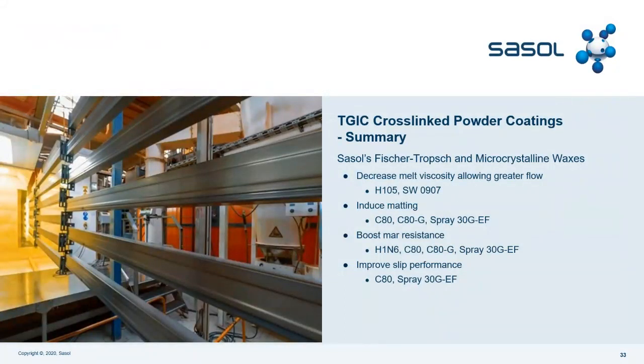So smart summary: in TGIC cross-linked powder coating, you can achieve with Fischer-Tropsch wax and with microcrystalline wax a decrease in melt viscosity, allowing greater flow. So means the performance and the improvement is in the flowability. You can improve with H105, Sasol Wax H105 is coarse powder, or with Sasol Wax 0907, that is the microcrystalline one. Or you can induce matting, with respect to polypropylene wax, with Sasol Wax C80, pastillized, C80G, micronized, Sasol Wax Spray 30 GEF, the ultra fine. You can boost mar resistance with H1N6 coarse powder, with C80, that is the pastillized version, with C80G, that is the micronized with melting point 80, and Spray 30 GEF, that is the ultra fine.